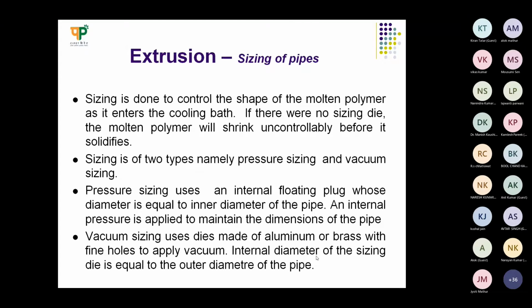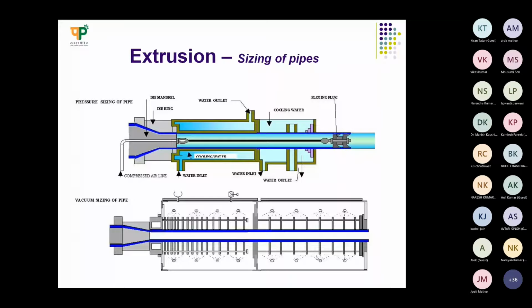See, the pipe's dimension has to be maintained. Inside you can introduce some pressure, air. So in that way also you can control the shape. Or you can send this extrudate into the vacuum system, so that also you can control the size. So this one is the first one, the plug system, where we have an internal plug and pressure is maintained. Once the melt is coming out, here like a diaphragm, like your air pump, similar way. Up to here the pressure is maintained, so that the diameter also will be controlled running through a sizing die, and inside the pressure is there, that will maintain the shape without collapsing the extrudate.